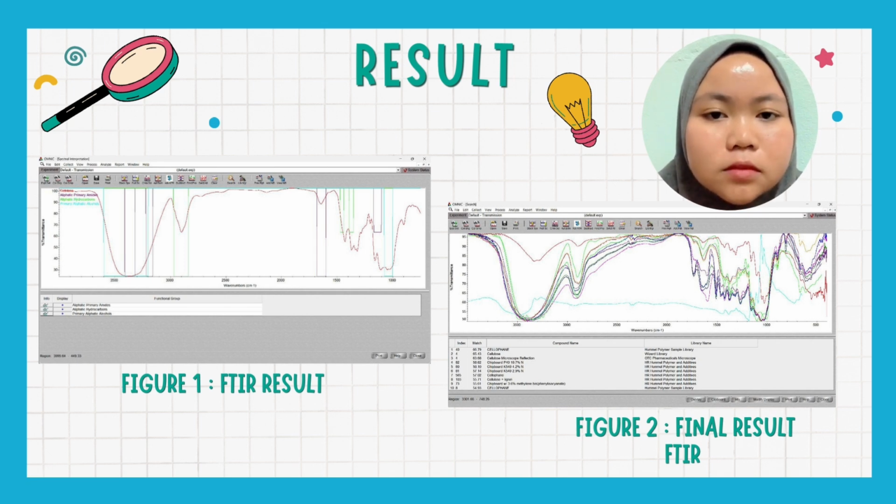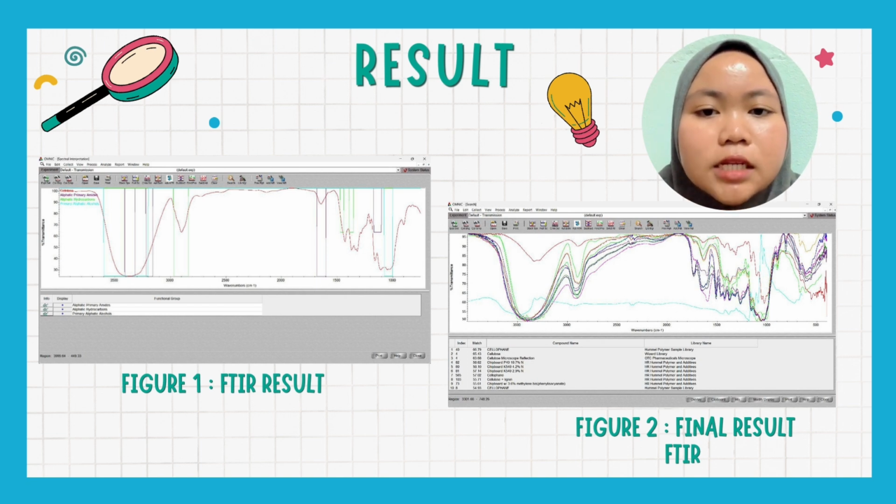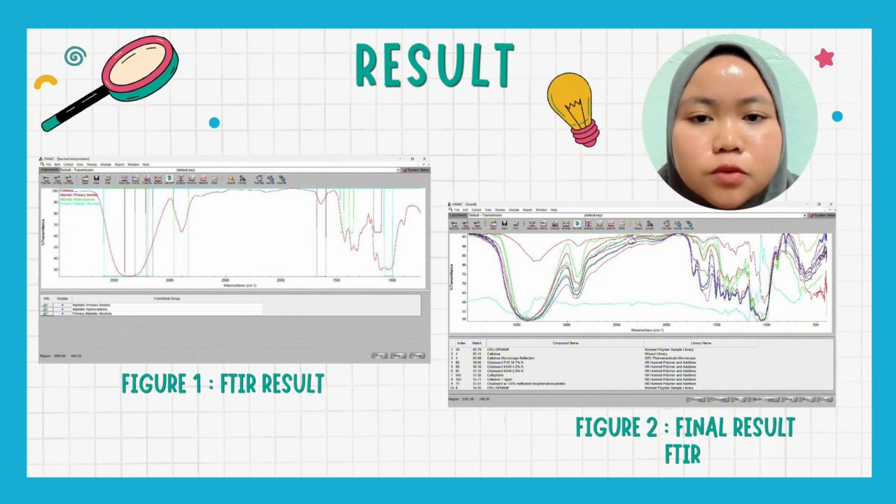1,640 cm-1 for CO stretch. It allocated hydrocarbon around 2,850 to 2,916 cm-1 for CH stretch, and primary alcohol around 3,200 to 3,550 cm-1 for OH stretch, and around 1,040 cm-1 for CO stretch. This suggests the sample contains a CONH2 group, a long carbon chain, and an OH group